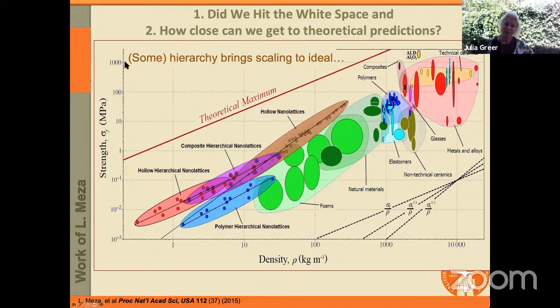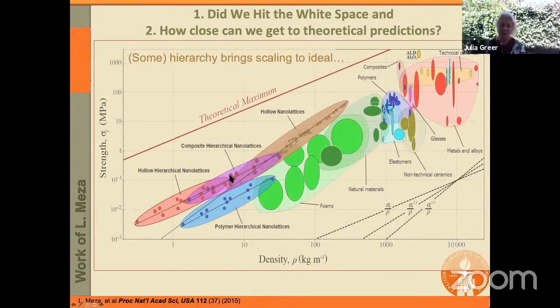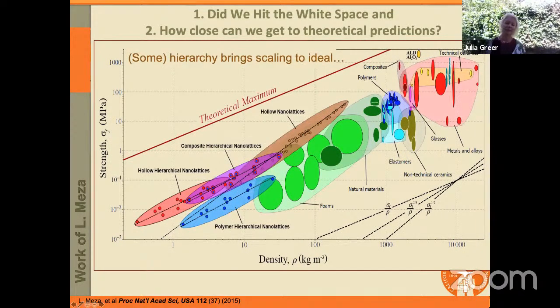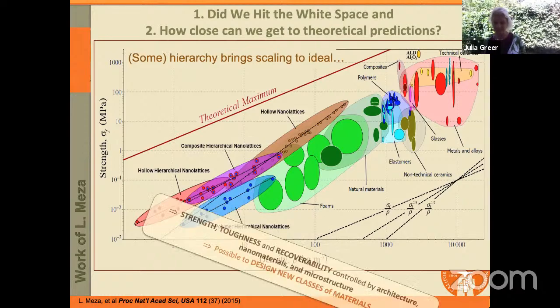So the plot that I showed earlier of strength versus density, these that you saw in these oblong regions are the data that we had taken through the years. And what you can see is that we already, for example, by creating hierarchical nanolattices, reduced the relative density of these architectures by 2 orders of magnitude. And we certainly have ventured into the white space. And this was at the time when we started doing this work, and we and perhaps many other groups can now do a lot better in getting closer to the theoretical maximum.